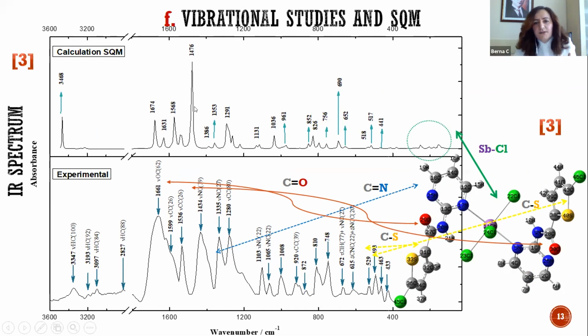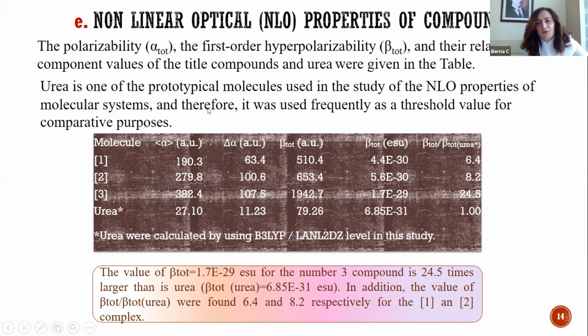Also the calculated IR spectrum is below, and the non-linear optical properties of the compounds section is here. The polarizability, first order hyperpolarizability, and their relative component values of the title compounds and urea are given in the table. Urea is one of the prototypical molecules used in the study of the NLO properties of molecular systems, and therefore it was used frequently as the threshold value for comparative purposes. The beta total value for compound number 3 is about 25 times larger than urea. In addition, the beta total values of the other compounds are less than that of number 3.